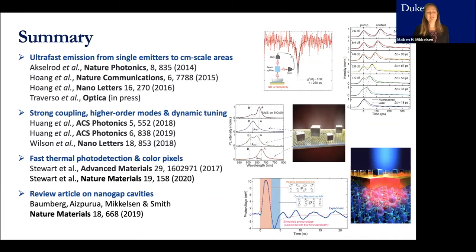Yes, that's a very good question, and that's very important. We often measure it if we can, right? So we can measure the dipole orientation. Often it can be tricky to control the dipole orientation. There are chemical ways that you might be able to control it. You may be able to pick emitters that have a preferable dipole orientation. For quantum dots, I think it was pretty much random, so that was taken into account in that way.